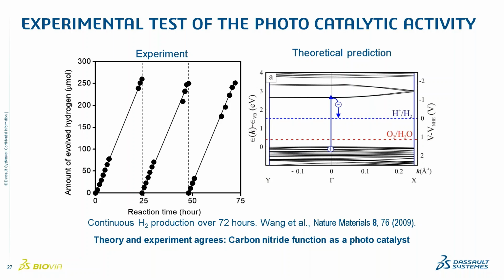So it confirms that what we did with the theoretical prediction, where we identified that the criteria for a photocatalyst was met by these materials, is also confirmed by the experiments. So we see that this screening procedure is able to identify from just in silico procedures if a material is a suitable candidate or not for photocatalytic activity.